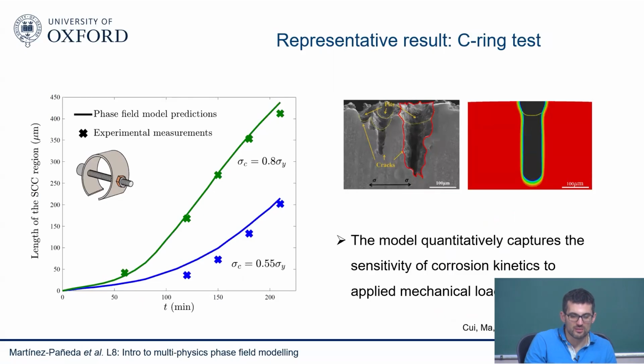And it's not only that the model seems to agree quite well with the degree of corrosion, but also the morphology of the corrosion front. So you can see here, these two images are using the same scale. And in the experiment there are multiple pits. We decided to focus only on one pit, the main pit, but you could model multiple pits if you wanted. And you can see that the morphology of the corrosion pits looks relatively the same. I mean, there's a bit of, I guess, microstructural influence here, but overall it seems to agree quite well. So I think it's fair to say that the model quantitatively captured the sensitivity of corrosion kinetics to applied mechanical load. So that's one ingredient, and we were happy with that.